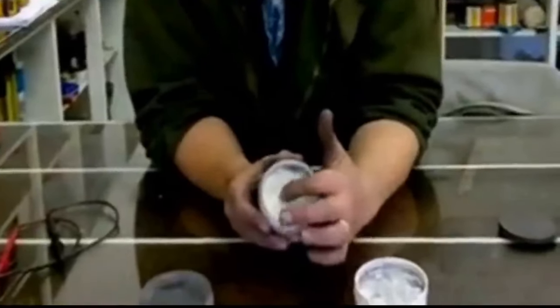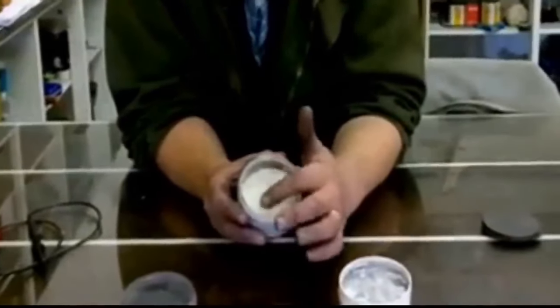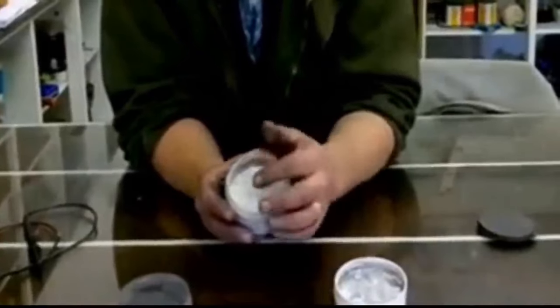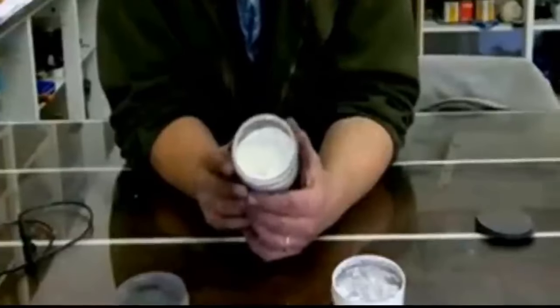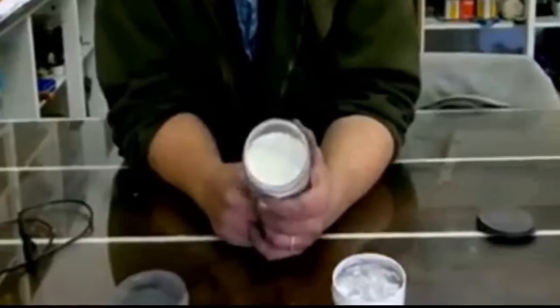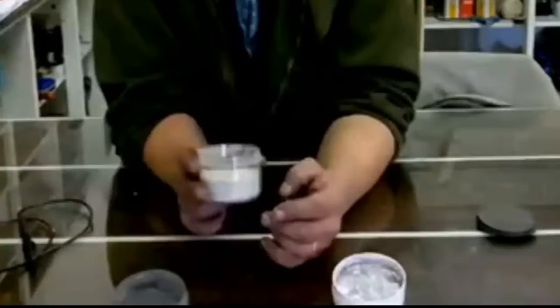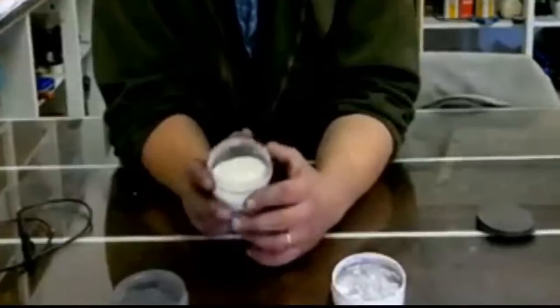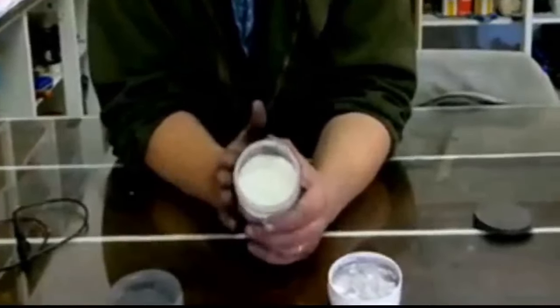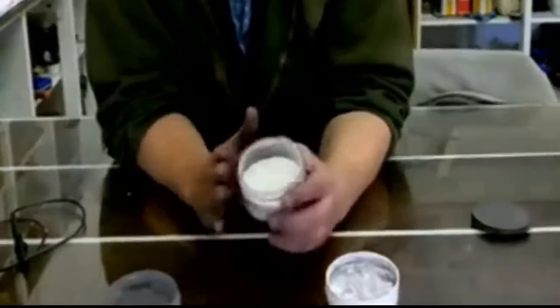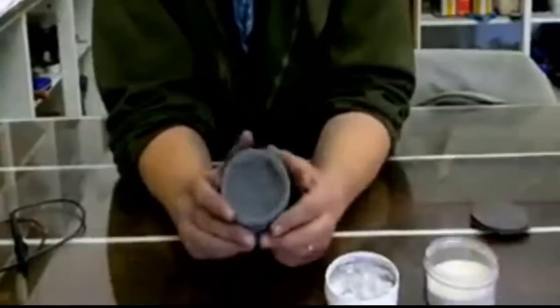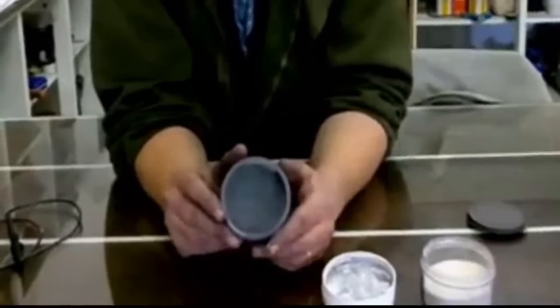Okay, when you've gone through that process, what you get is this white powder, and this is just powdered casein. Now what we do to that is add 0.5% of graphene powder to it. You really don't need to add a lot to get an enhancement. And we only added 0.5% because it was completely random, we just chose something. And it turns it into this silvery powder.